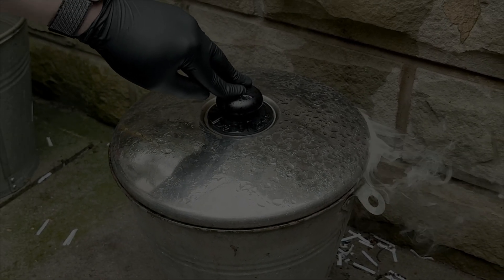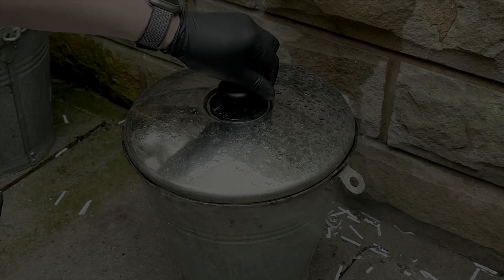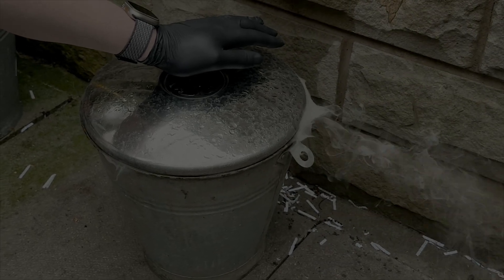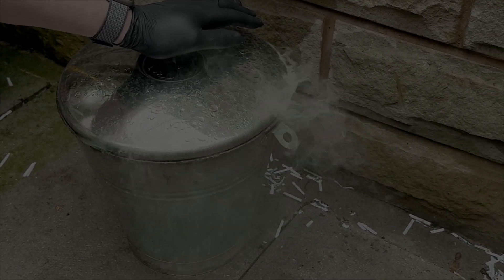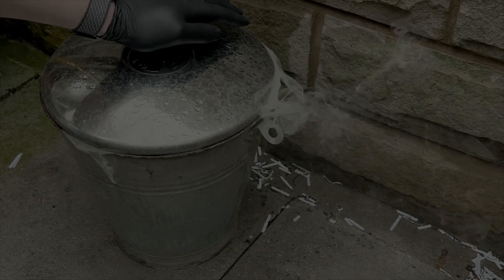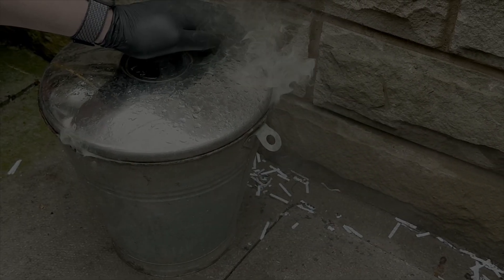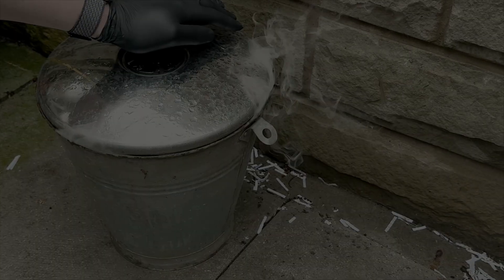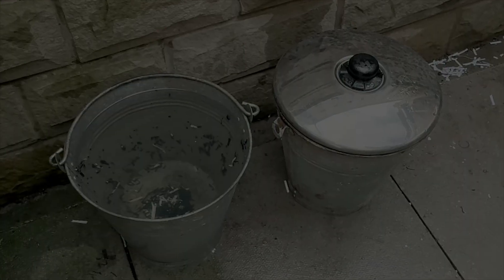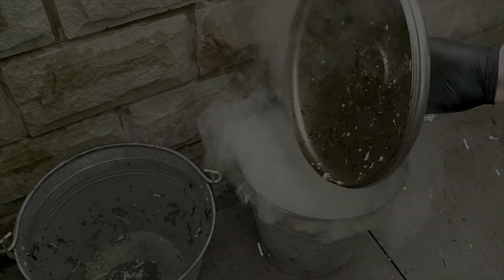This is a reduction process. The reason you need a tight-fitting lid is to cut out any oxygen so you can do the reduction process properly. Everything that's not glazed — the raw ceramic — will turn black because of the reduction, which is awesome because you can create some really nice effects by not glazing certain parts of your piece. Five minutes gone — ready to open it. Very smoky!